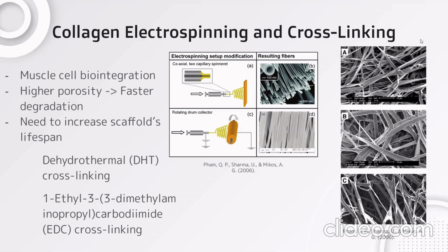Another option is EDC cross-linking, which stands for a chemical I will not try to pronounce, but it is a chemical process that greatly increases the strength too, but also increases cost and manufacturing time per implant. Because of that, we will not use it, but in case in preliminary testing, DHT cross-linked meshes are not strong enough or don't last long enough, we will add EDC cross-linking into the mix to hopefully get a stronger implant. On the right side, just for reference, you have on the top a DHT treated collagen mesh, then an EDC treated collagen mesh in the middle, and finally a DHT EDC treated collagen mesh on the bottom.